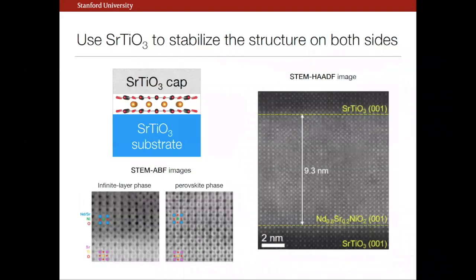And so the final step in this initial foray was then to say, if that's kind of giving you a stabilizing proximity effect, let's do it from either side. And so here you can see a reasonable early sample where we have now packed this perovskite nickelate with a layer of strontium titanate. And I'll come back to a more detailed discussion in a moment, but we can see that indeed it's normally this infinite layer phase throughout. And as I'll show you, we've made some improvements, but right now our approach still has this kind of thickness limit, meaning our best uniform single crystal thin films are limited to about 10 nanometers. So that's our current situation.